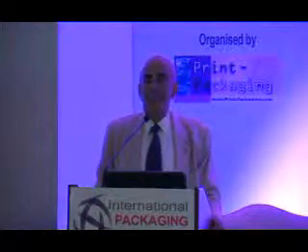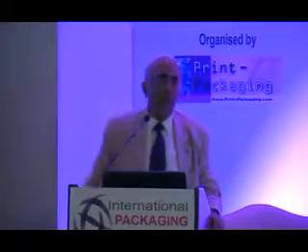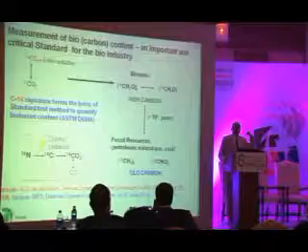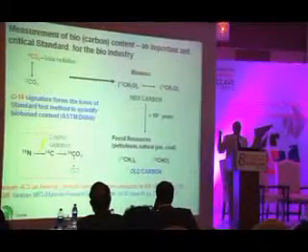Any carbon product made from fossil, because it is over millions of years, has no radioactive carbon signature associated with it. I burn your product, I measure the C14-C12 ratio, I compare it to a standard, and I can tell you accurately, plus or minus 3%, what is the bio-based carbon content of your product.